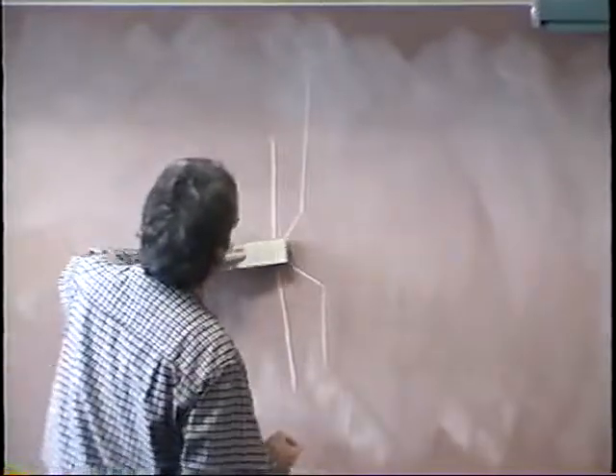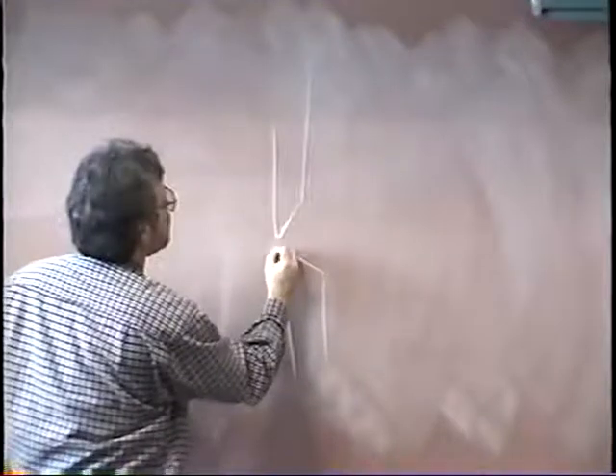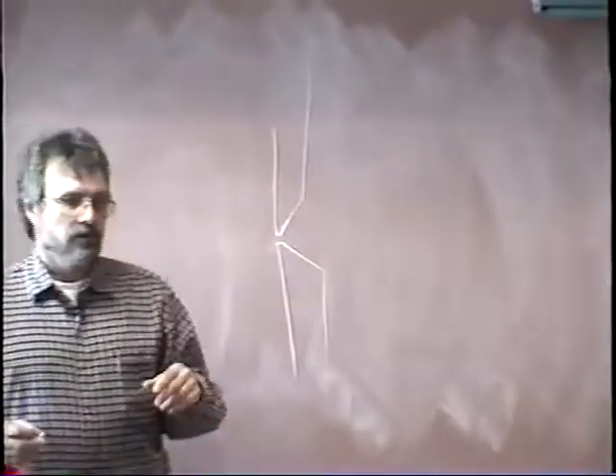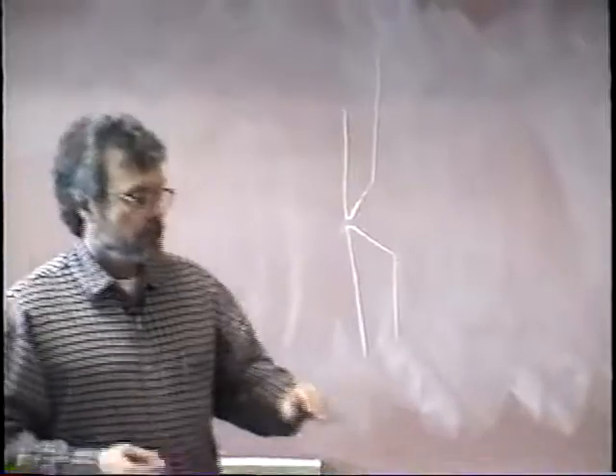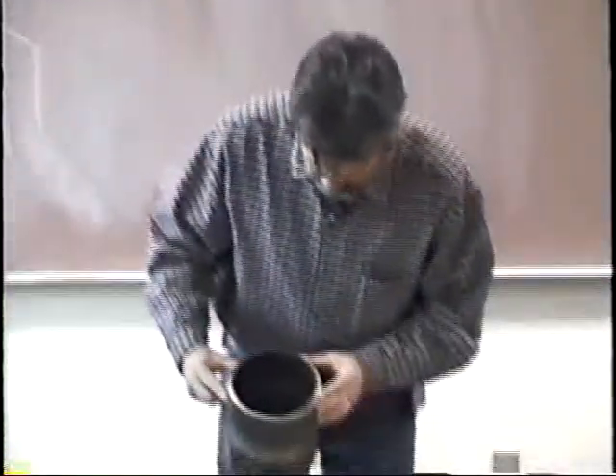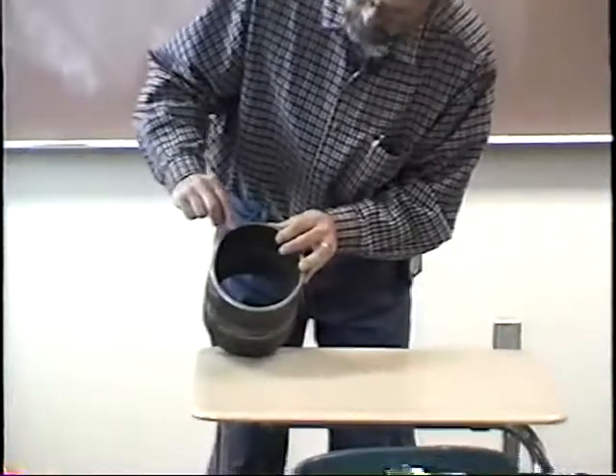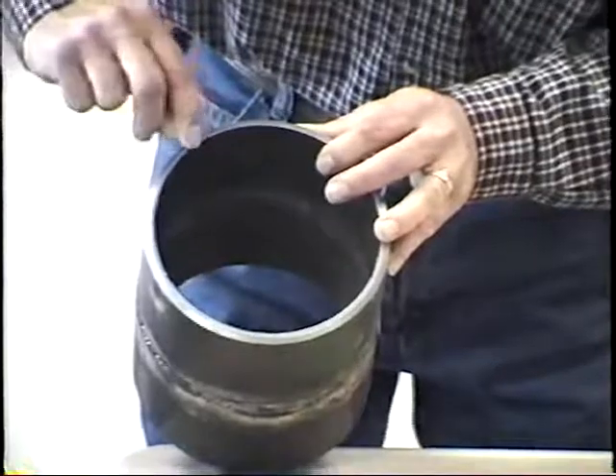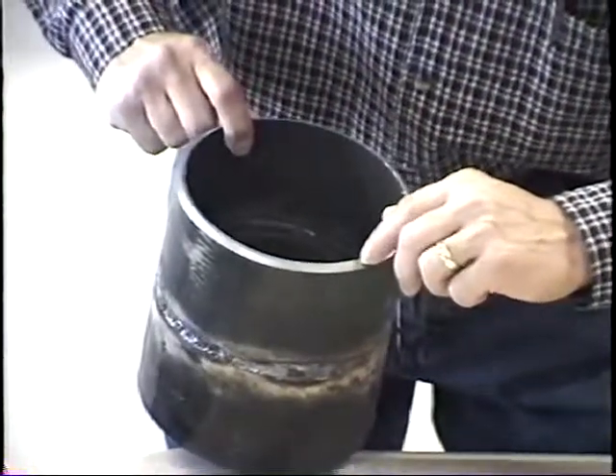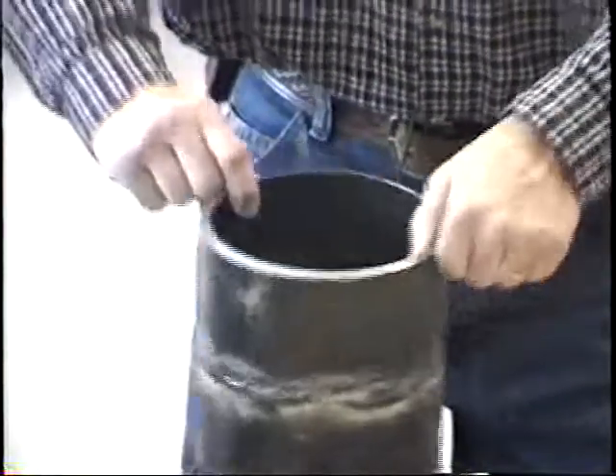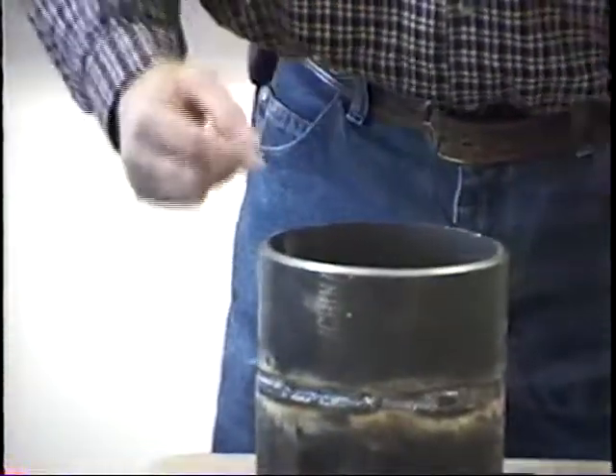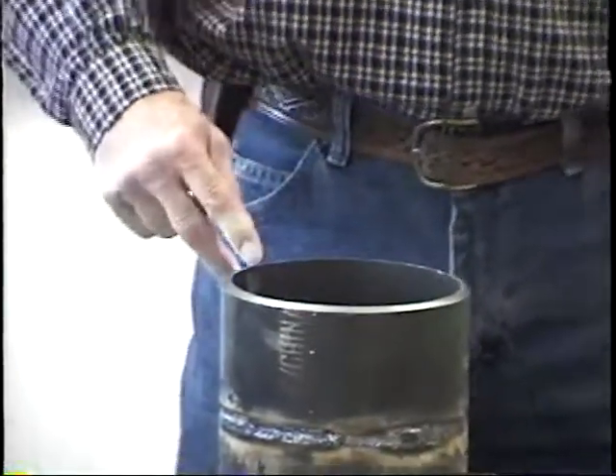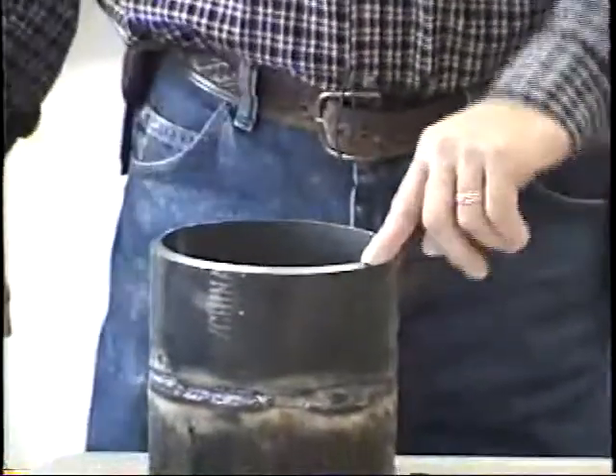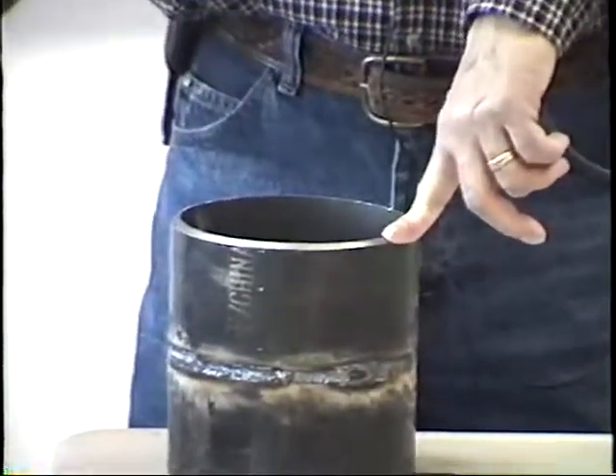Then the other thing, and I'm really glad he mentions this, it's going back to our land, our root face reinforcement right here, the root face. If this is too thick, and Paul, you know this especially, you'll come to find out about it. On this pipe, this is not a bad example. Right here, this part of the land is about a 1/16 of an inch thick. But over here on the opposite side, this is about 3/16 of an inch thick. So if you were to fit this pipe up and you set your heat to where it's just right for this 1/16 of an inch, and you got good penetration, you're welding on around it, you get to this part where it's 3/16, there's too much meat there, you're not going to be able to penetrate it.